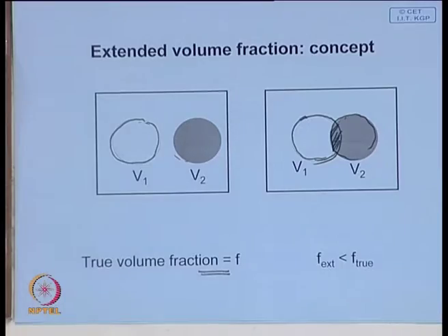We shall look at how, with this concept, it is possible to derive a definite expression for fraction transformed, say for transformations like the pearlite transformation or any diffusion-controlled transformation. This in fact will be even applicable to precipitation kind of transformation. The only difference is that in the precipitation process in a supersaturated matrix, the volume fraction of precipitate is very low, very small. So, the question of impingement does not come there, since the volume fraction will be so low that impingement may not be necessary.